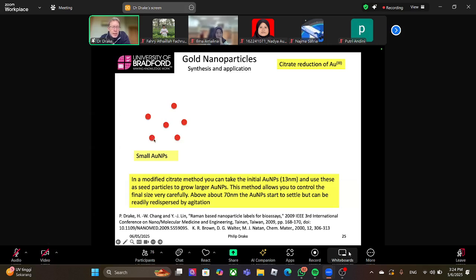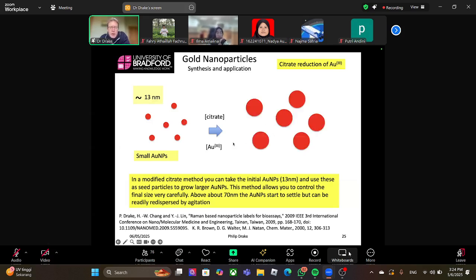So you take your pre-made particles, about 13 nanometers, you add in some more citrate and some more gold chloride, and they can grow to give you larger particles. Now, there's no nucleation because we're using these as the nucleation sites. The more of these we add, the smaller the particles; the fewer of these, the bigger the particles. So we can control the size of the final particle by controlling the amount of nucleation sites or the amount of gold added. We can aim for very precise sizes. And this can make particles from 20 to 100 nanometers in size.